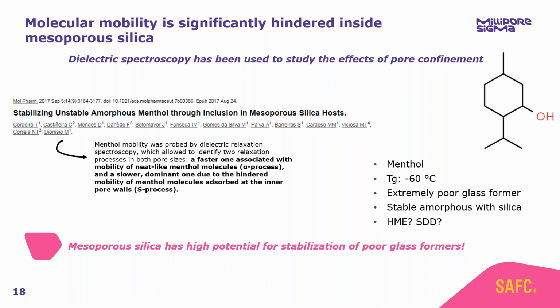To put that into context, menthol has a glass transition temperature of around -60 degrees Celsius. So there's a standard rule of thumb that those of you working on this might know, that if you have a molecule with a glass transition temperature, you need to store that formulation at 50 degrees lower than the glass transition temperature, just to be totally certain that your formulation will not recrystallize.